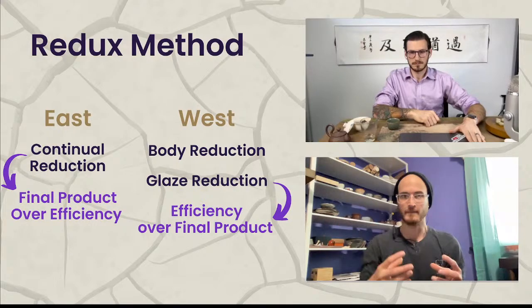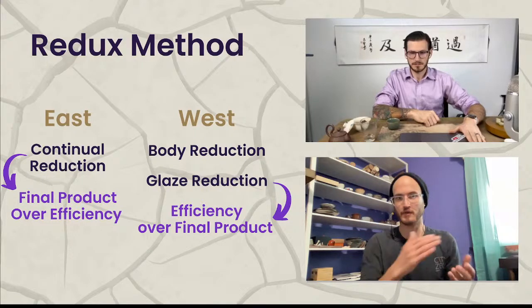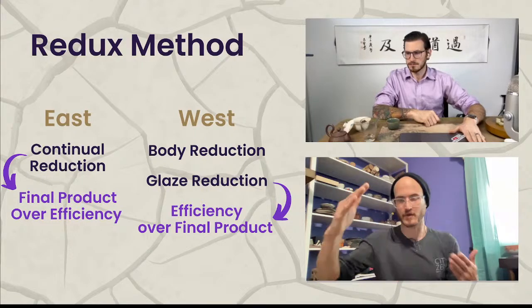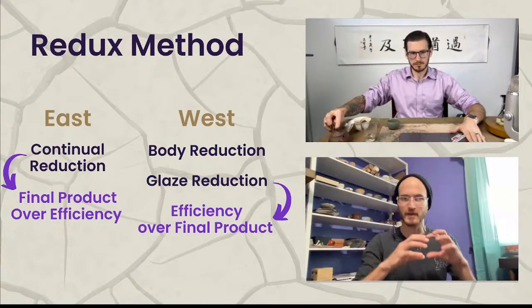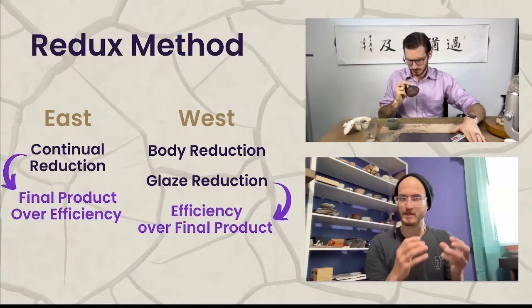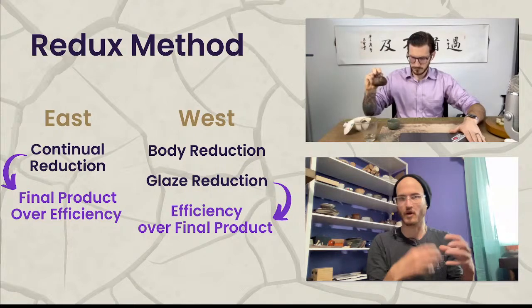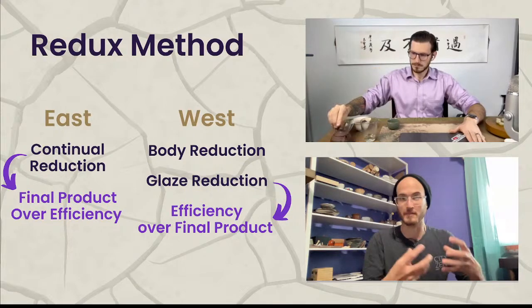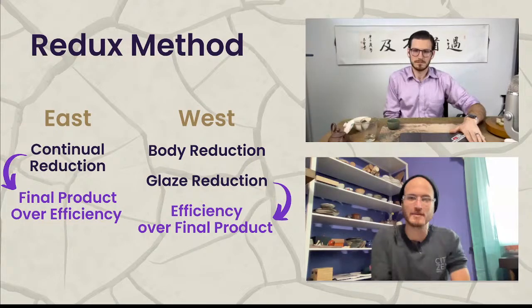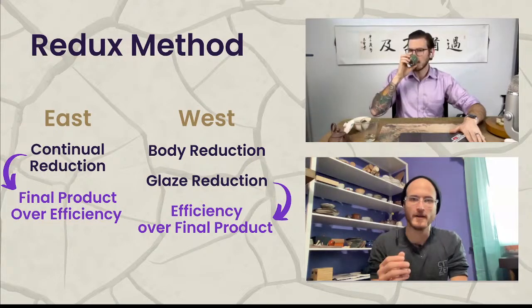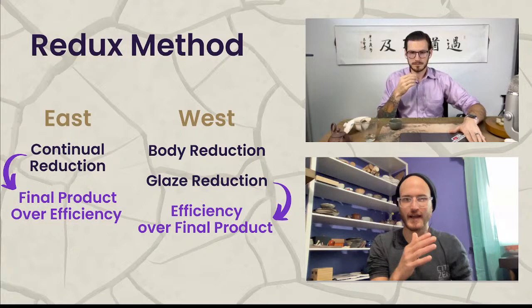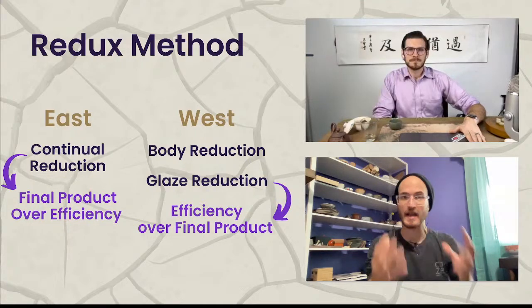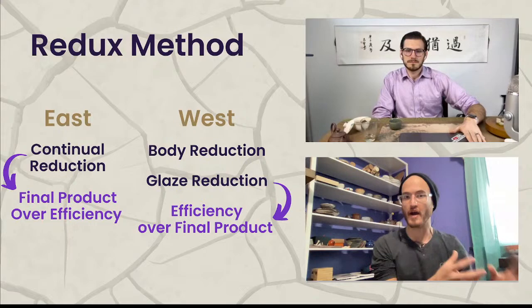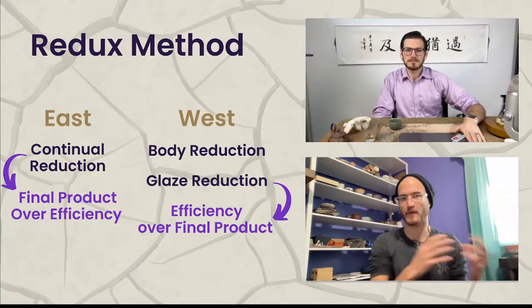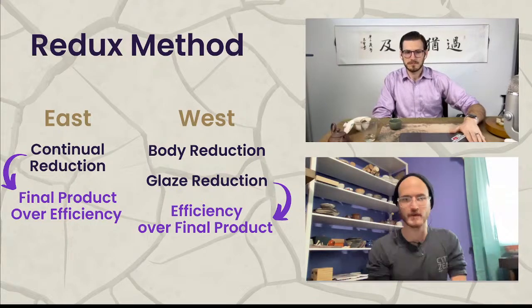Because there are certain things like that metallic sheen that my clay can have that can really only be developed over time. If you did 2 spurts of reduction and that's all you did, you would never get that surface developing because it really has to interact with the clay for a long amount of time. Whereas, in the US, most of the time we're just focused on firing and glazing and creating things that respond well to the firing process versus changing the firing process in order to get the result that we're looking for as a final result.